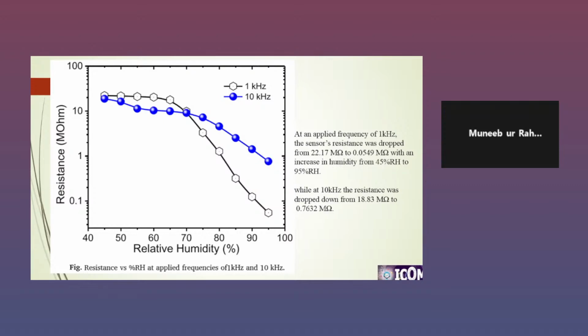We can see in the next few slides how this conduction mechanism occurs. This H plus ion moves toward one plate, and the OH ion, which is a negative ion, moves to the other plate depending on the polarity. So due to the water molecule, we see that the resistance is initially high at 45% relative humidity, and it decreases gradually.